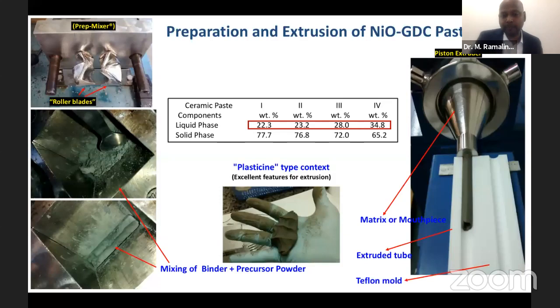Here you can find how much liquid phase and solid phase are in the paste. For making the paste, we mix the polymers that I mentioned in the composition in the previous slides, and make a mixture. And from this paste we extrude.